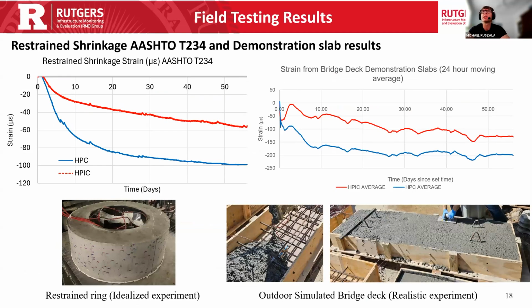And maybe the highlight of this program was the restrained shrinkage testing, which is a bit of an advanced test. We did the laboratory restrained ring test. So you can see these very clean results with a very high degree of reduction in shrinkage strain by the HPIC. And you can see that reflected in the simulated bridge deck slabs that had the sensors embedded in them. This was about 8 sensors for the HPCs and 8 sensors for the HPICs. So averaged together, you can see the result. It's a significant decrease in the shrinkage for the HPIC material, which in a highly restrained bridge deck,